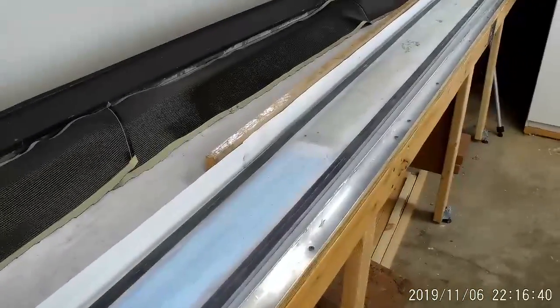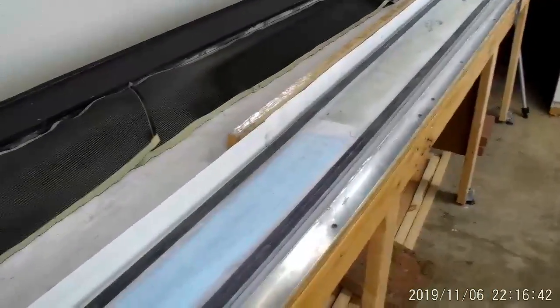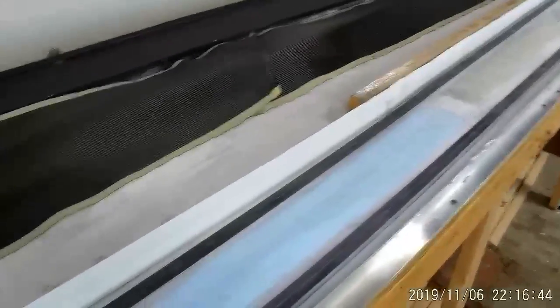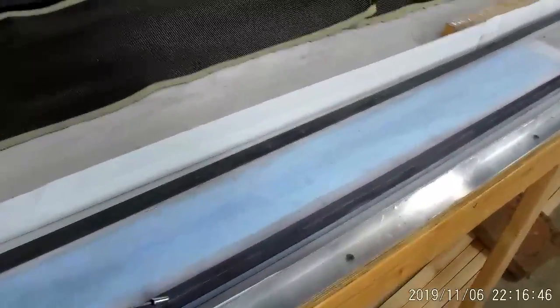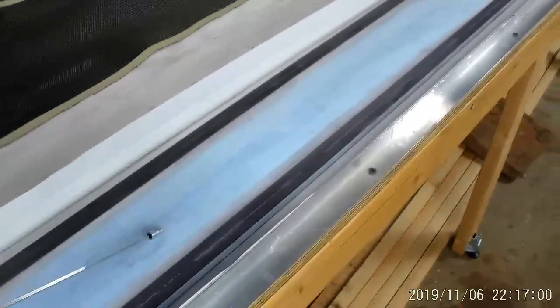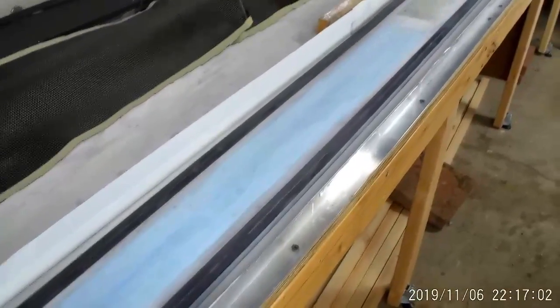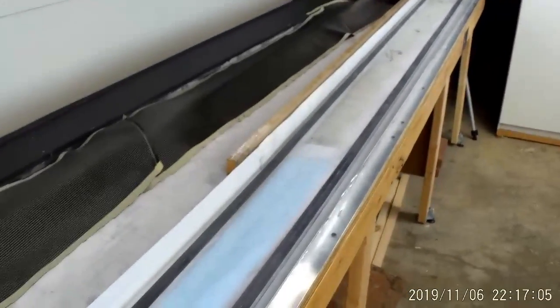The PVC foams are resistant to most solvents that you would use to clean the cap strips before you bond to them, but the polystyrene is susceptible to most solvents except for alcohol. And therefore, when I clean these cap strips prior to laying up the face sheets, I'll be using alcohol to clean them so that I don't damage this foam. If we damage this foam, the entire spar would be lost at this point, and that would be a big dollar and labor loss, so we don't want to make that boo-boo.